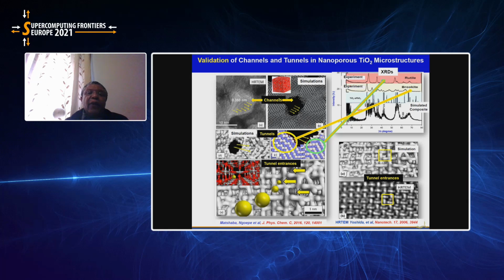Now, in this one, we have a nanoporous structure of titanium dioxide with its microstructures. And we see here again the channel through which the electrolyte can move. We see the tunnels here marked in red. And these tunnels are seen to be having zigzag patterns corresponding to the brookite phase and the straight patterns corresponding to the rutile phase.